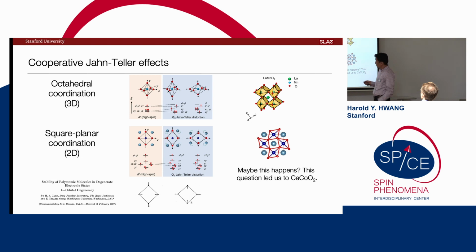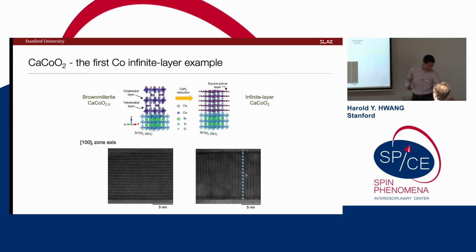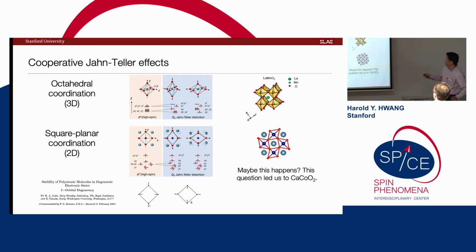Yeah, so I learned about this from Andy, actually, right? So I was kicking around as a student at Bell Labs, working on manganites. And this has this famous story that it's a strong Jahn-Teller ion, and there's a lattice of them. And nature comes up with a very clever way to have nominally a volume-preserving Jahn-Teller distortion that is on every site, by taking a long axis alternating here, there, and everywhere, right?